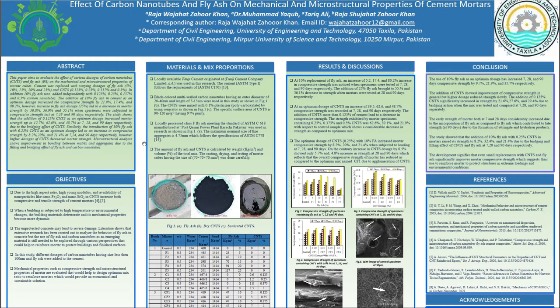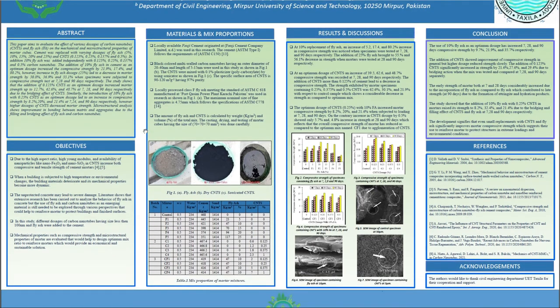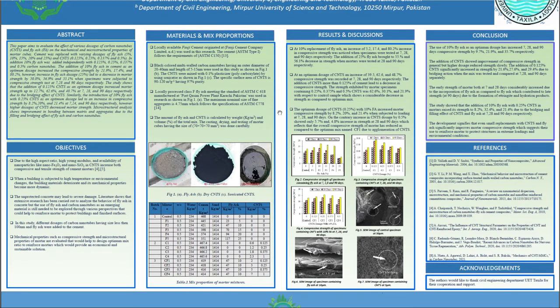In this study we used materials including cement, carbon nanotubes, fly ash, and fine aggregates. The mix proportions were divided into three categories: the first replaced cement with fly ash, the second replaced cement with carbon nanotubes, and the third combined the optimum fly ash dosage with different dosages of carbon nanotubes. Since carbon nanotubes are very fine carbon particles, a sonication process was used to disperse them.